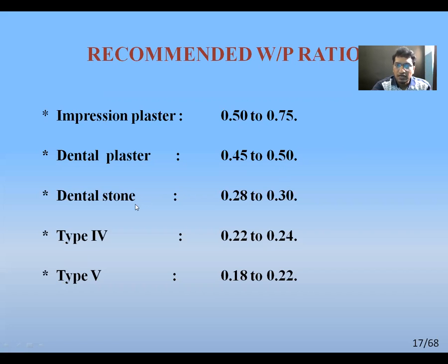Same for dental stone, I'm going to mix 100 gram of dental stone and need only 28 to 30 ml of water to mix the same amount of plaster or stone. And likewise, type 4 is 0.22 to 0.24, and type 5 is 0.18 to 0.22. So the more the water powder ratio, the less is the strength and the more is the setting time.